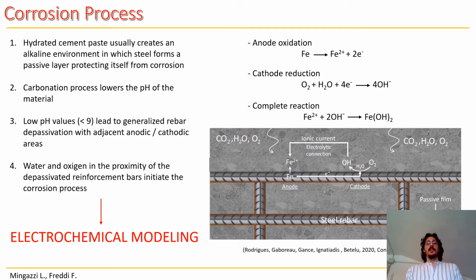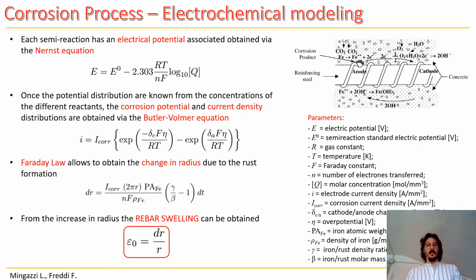In order to model the corrosion process, we adopted an electrochemical modeling approach. The electrochemical modeling for the corrosion process is structured as follows. First, we calculate the electrical potential for each of the two semi-reactions via the Nernst equation. Once we have the two potentials, we can obtain the value of the corrosion current density using the Butler-Volmer equation.